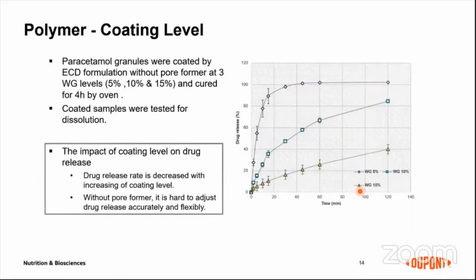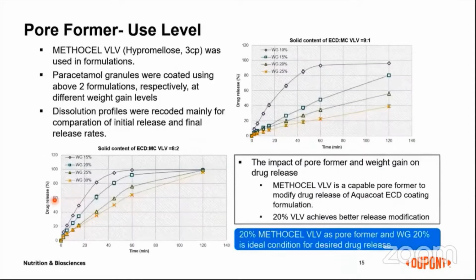So then we can see the drug release results in terms of the impact of coating level. So when there's no pore former in the coating formulation, when we increase the coating level from 5% to 15%, actually we can easily decrease the drug release. But without pore former, it's hard to adjust drug release accurately and flexibly, right? So which means we need to think about adding pore former in the coating formulation. So basically we can see the impact of pore former and the coating weight gain on drug release.